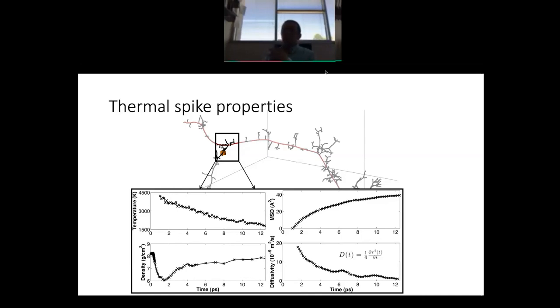Obviously, if we make the interface thickness comparable to the layer thickness, then the model becomes unrealistic because it is no longer able to represent the fact that the multilayer is stable without radiation, right? So if we had a phase field model where the interface thickness is comparable to the layer thickness, then those layers would automatically interact with each other in the phase field model, and that would be unphysical. So we modified the interface thickness to within about a factor of 2, and that did not influence our conclusions,